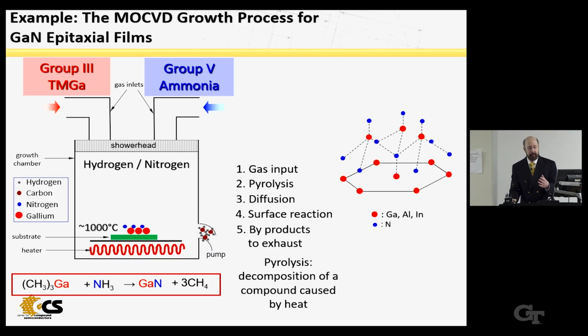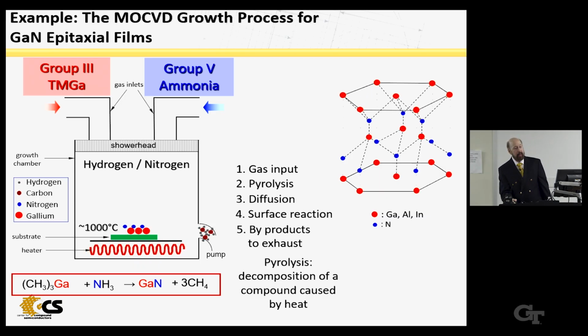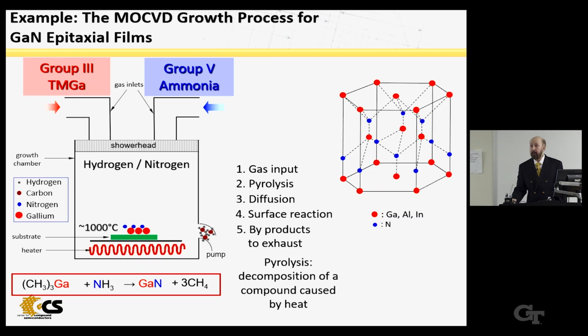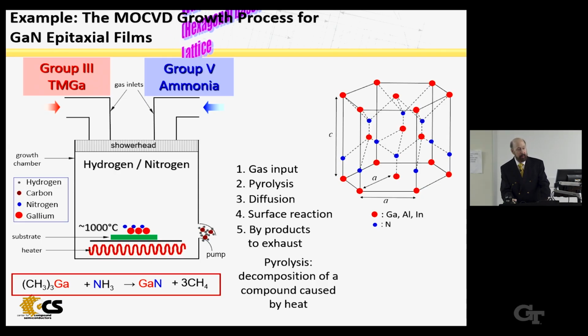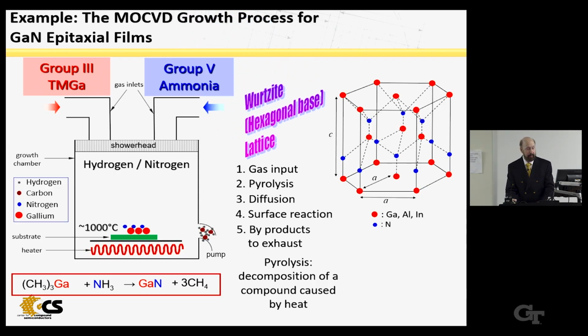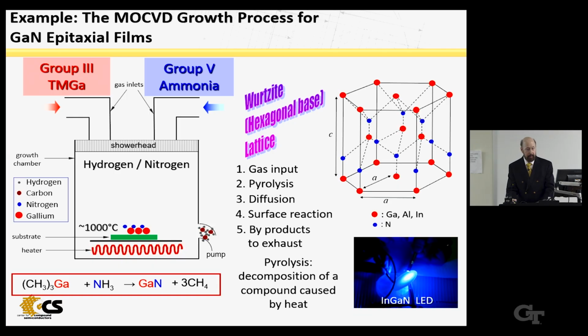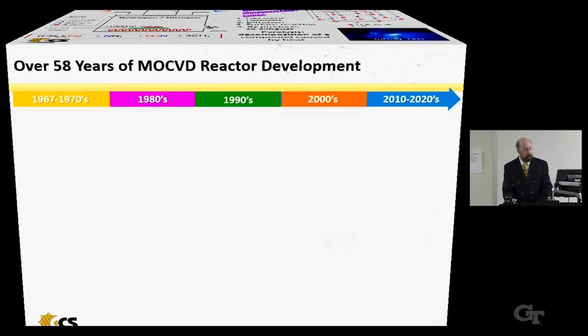Well, Mother Nature does this for us because atoms are always seeking the least energy position on the surface. And we've given enough energy by heating it to 1,000 degrees. In the gallium nitride case, or the indium aluminum gallium nitride case, we get a hexagonal crystal. And with that technology, we can easily grow GaN LEDs as shown here.